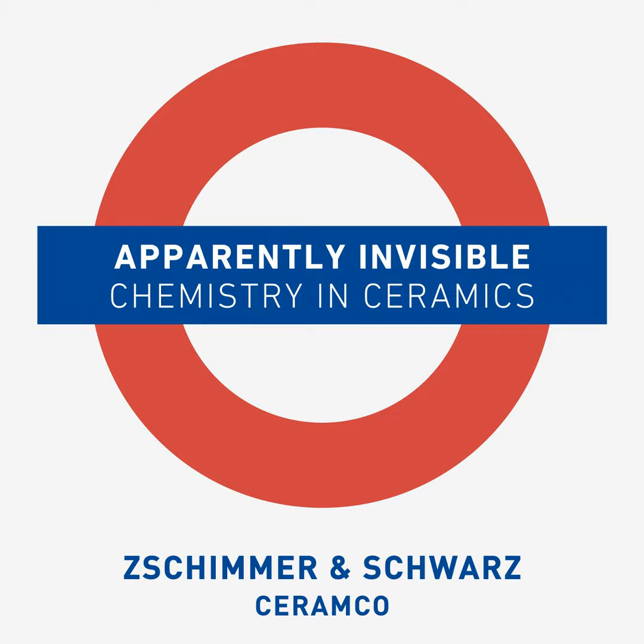Let's start from the beginning. Leaving aside digital printers, we will focus on what concerns us more closely by immediately making a list of the most important components of water-based digital glue. Chemically speaking, water-based digital glues can be generally considered as organic polymers and inorganic components, when present, in water and polar solvents. Their composition is generally made of 35% water, 45–55% polar solvents and resins, and 10–20% organic components.